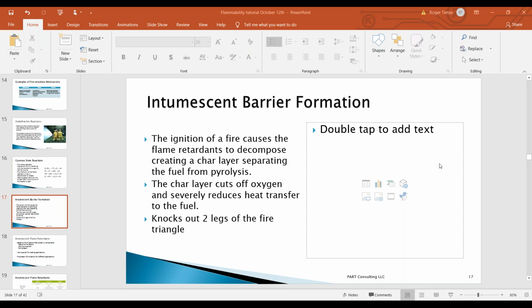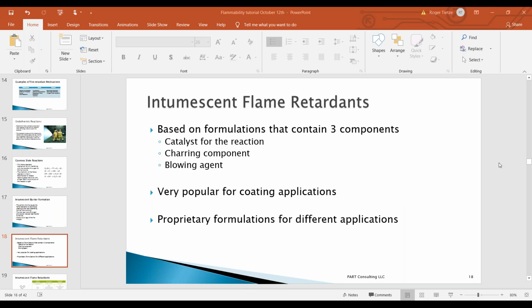The problem is that eventually you'll add so much silica that you'll end up having a problem as far as having a workable formulation that can be processed. So there's really not many silica-based flame retardants. It's an inert filler material, and it can reduce flammability. Okay. With that, we'll go on to the next slide for intumescents.